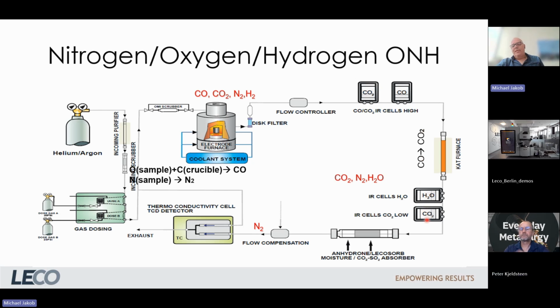Then we detect CO2 with an infrared cell, the same infrared cell you saw before on the carbon-sulfur analyzer, the same type of infrared cell. Keep in mind, this catalyst furnace also transfers hydrogen to water, which means we detect water also with another infrared cell. So we have oxygen and hydrogen. Unfortunately, there is no IR cell for nitrogen, so we have to detect it with a thermal conductivity cell, the TCD detector. And before we run anything on the TCD detector, we have to remove all other gases that could influence the thermal conductivity. This is done by a chemical, we call it Lecosorb, but it's more or less sodium hydroxide on a sort of clay carrier.